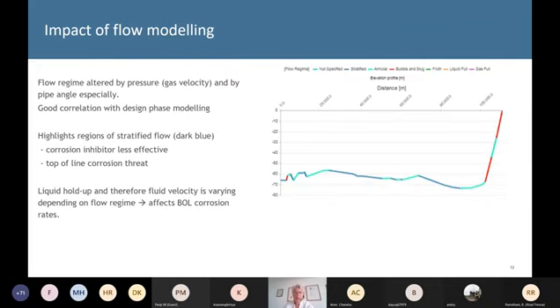Now, what happens when we look at a pipeline elevation, as you see on the right here? This is a typical pipeline that's running along the seabed, and then it's coming in on a shore approach coming up to the landfall here. So it's about 70 meters deep at the deepest. And we see a variation in flow regime, areas that are stratified, some upward going areas that are annular, and some areas going up that are bubble and slug flow, flowing from left to right in this diagram here.